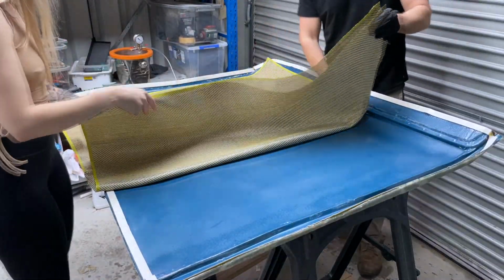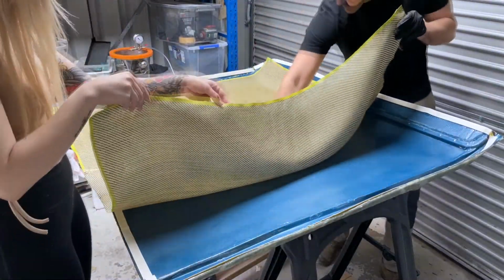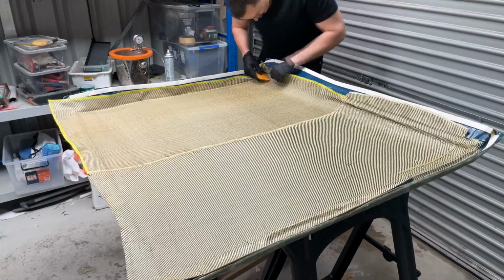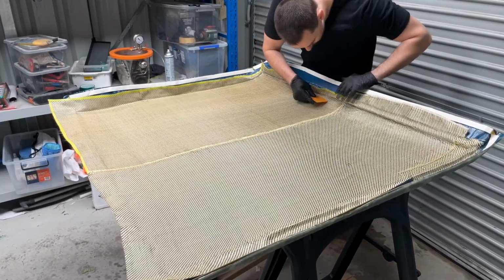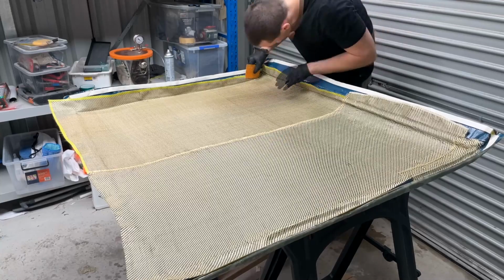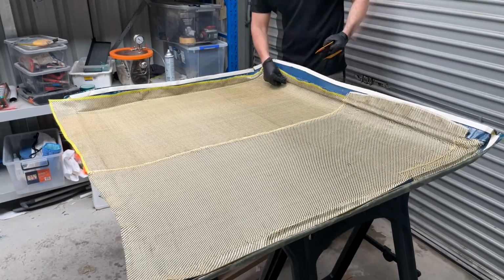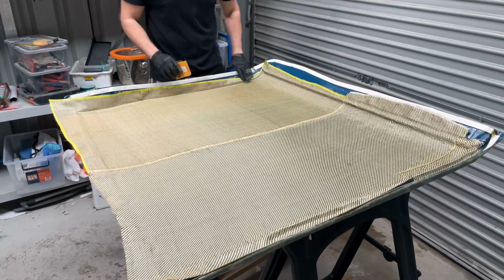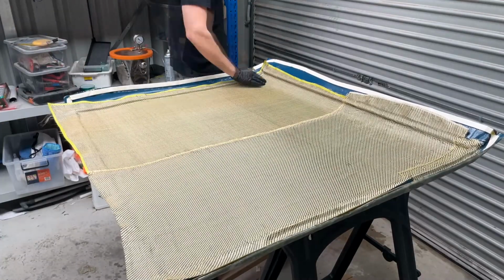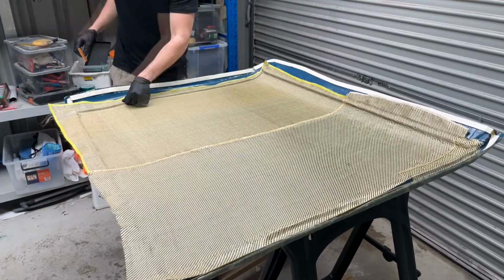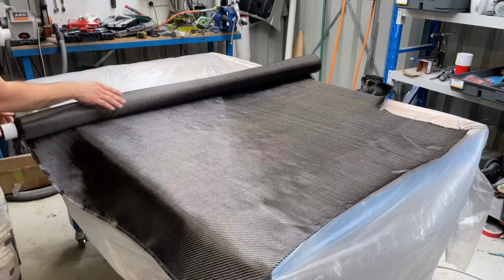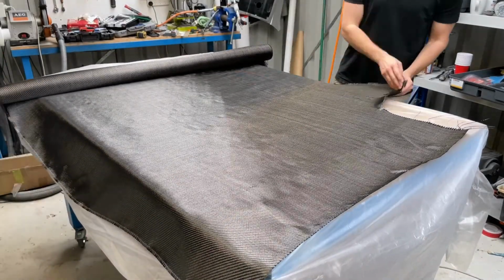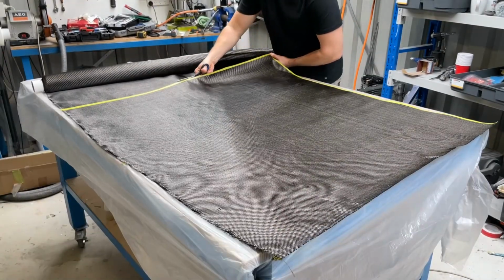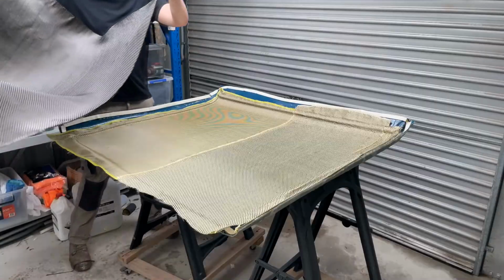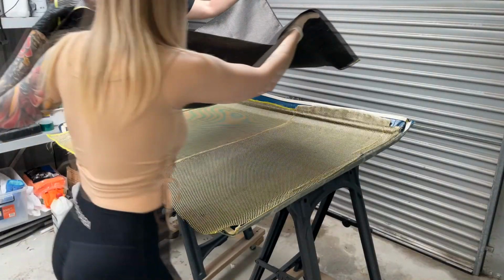The next thing I'm doing is using some spray adhesive and a small squeegee to really force all the fabric into the corners of the mould. This is a really important step because if you don't do this, sometimes the fabric can sort of bridge through the corner of the mould, meaning that you end up with some pretty bad air bubbles on the corners of the final piece. Next up is the first of the two carbon fibre backing layers, just using a standard carbon 2x2 twill.